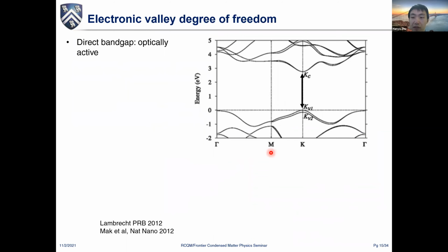Now let's look deeper into the band structure of this material and see how these electronic properties help us to interact with phonons. Other than being direct gap, the gap is actually located at the K point. So this is basically a green light, because both the electron and the hole, once generated, have enough momentum to scatter phonons. So you can study electron-phonon scattering with finite momentum.